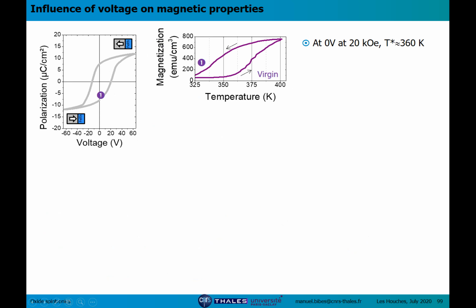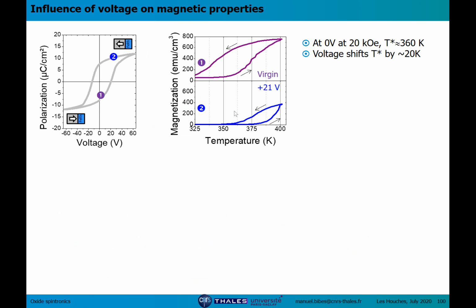Then when we measure the magnetization of the sample, so basically we measure the iron rhodium, this is what we get. This is a zoom of the data. You see the first order transition from the antiferromagnetic state with low magnetization to the ferromagnetic state. And then when we come back, there's hysteresis because it's first order. This is at 0 voltage. Now we do the same, but we apply a voltage across the material, and the transition is shifted by about 20 Kelvin to higher temperatures.